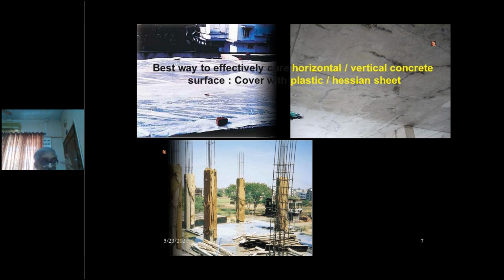Now you see the best way to do curing is immediately as the mason finishes the slab, just put plastic paper or plastic over the entire slab. The one on the left hand side top corner, this is the best and the cheapest remedy. The thickness of the plastic does not matter so long as it does not allow the water to evaporate into the air above. But always weigh down the plastic with some brick or something else, so that it doesn't fly away.